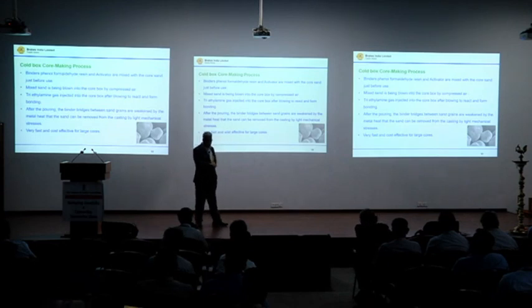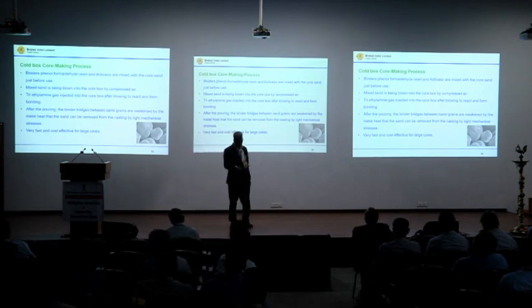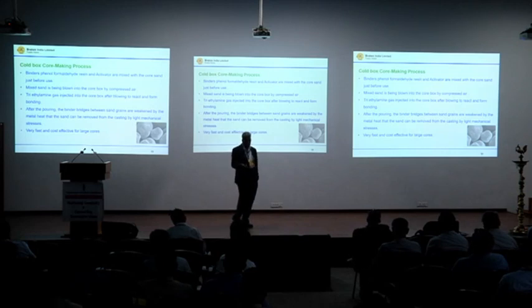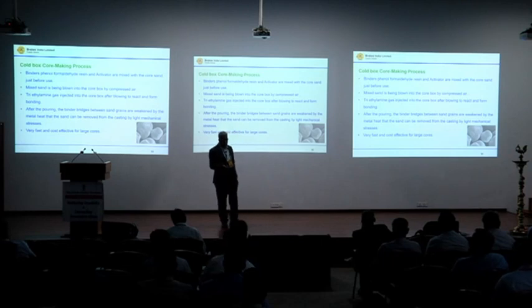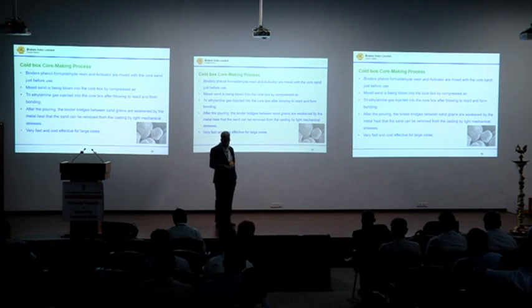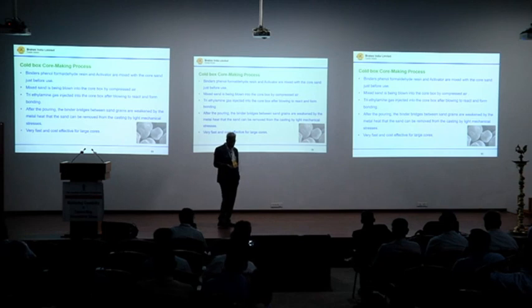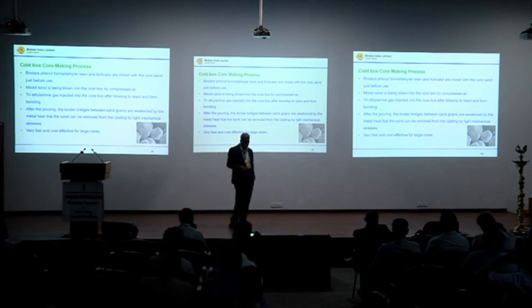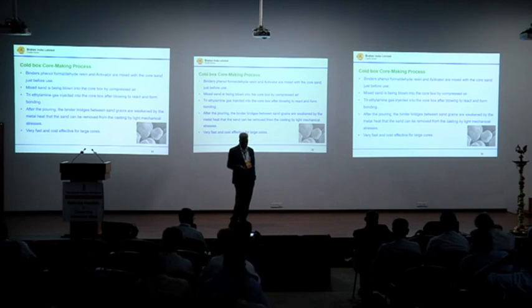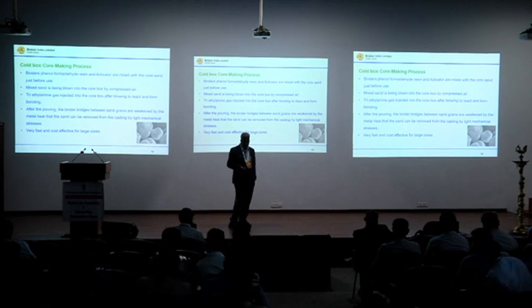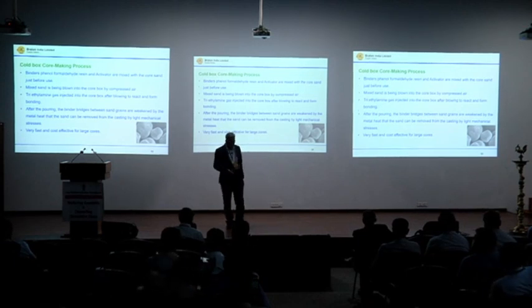This is a typical process of cold box. Phenolic binders, resin and activators are mixed with the core sand just before use. Mixed sand is blown into the core box by compressed air. Then amine is injected into the core box after blowing to react and form bonding. After pouring, the binder bridges between the grains are weakened by the metal heat so that the sand can be removed from the castings by light mechanical forces. It is very fast and cost effective for large castings.